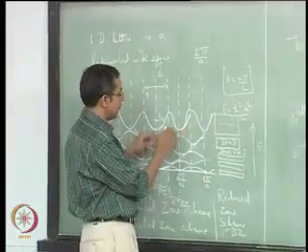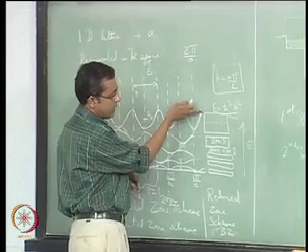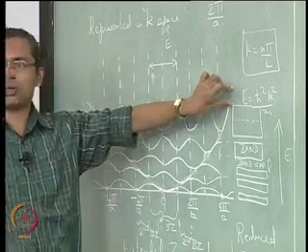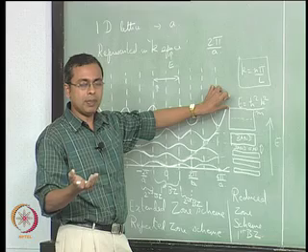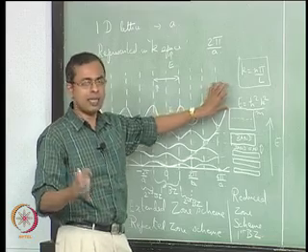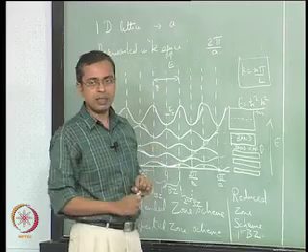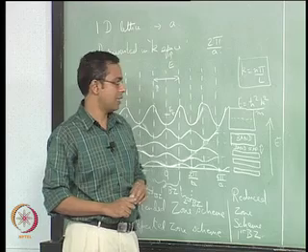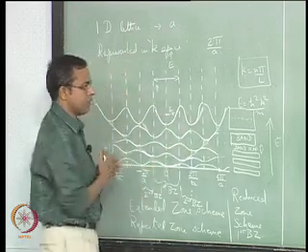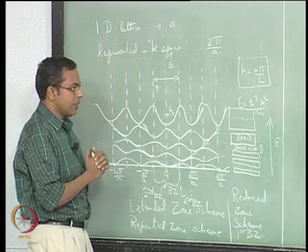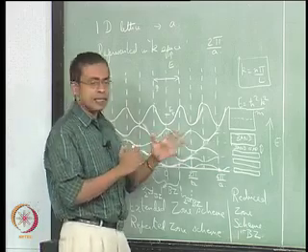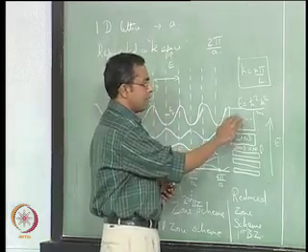On the other hand, you could have a Fermi energy which finishes right at the top of this band. In that case we will look at the band gap ahead of it. If that band gap is of the order of 2 electron volts or less, then that is a semiconductor. If it is of the order of 4 electron volts or higher, we would call it an insulator. So, we will look at the band gap. We will see that discussion in greater detail when we talk of semiconductors. So this is all the information that we have seen. In terms of the material property, the position of the Fermi energy with respect to these bands is a very important piece of information.